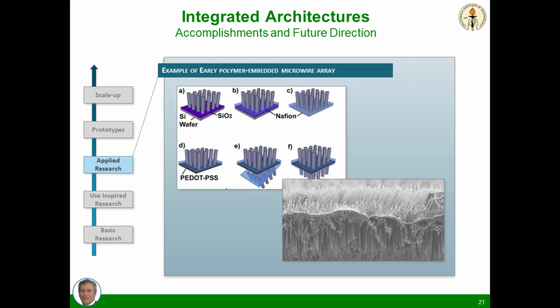This article of manufacture, this dual microwire array, really looks like our vision. It has all the characteristics. We've shown it prevents gas crossover, it passes protons or hydroxide depending on the membrane. If it's a Nafion membrane, it passes protons. If it's the alkaline equivalent, it passes hydroxide ions. It does everything except split water, because silicon on the top is oxidatively unstable. And I already told you that two silicon electrodes still do not provide us sufficient voltage to do the chemical fuel formation that is mandatory for the system to work.